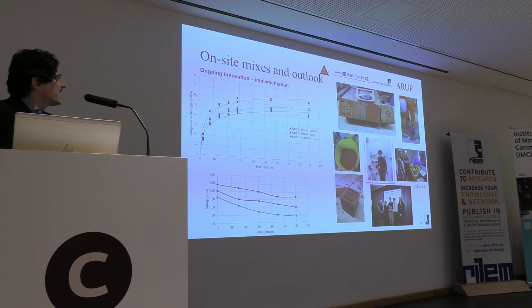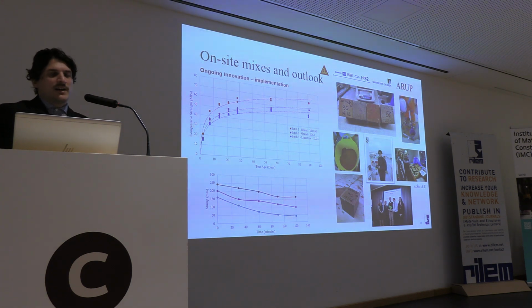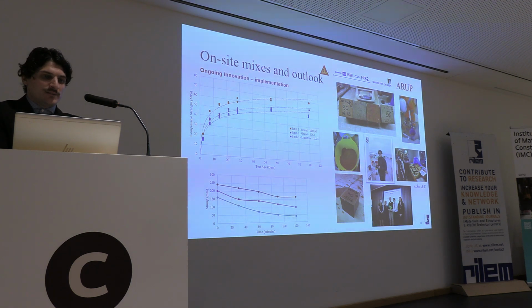And we can see that still, for these three different mixes, I think with 50% calcined clay, we can easily get into the structural concrete range, which is 40 to 60 megapascals. And many people complain about the workability and the workability retention of these mixes with calcined clay. Yes, it can be a problem, but with appropriate engineering and with appropriate use of admixtures, we can produce concretes with very good workability, which has been retained up to 2 hours at a very satisfactory level.